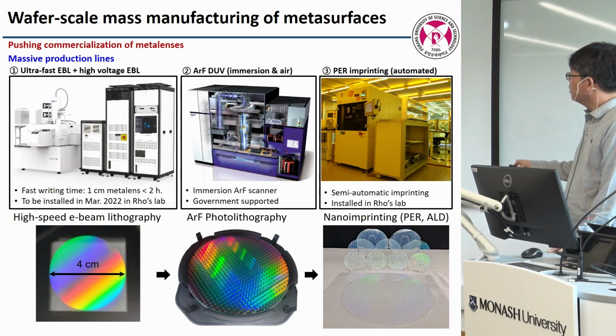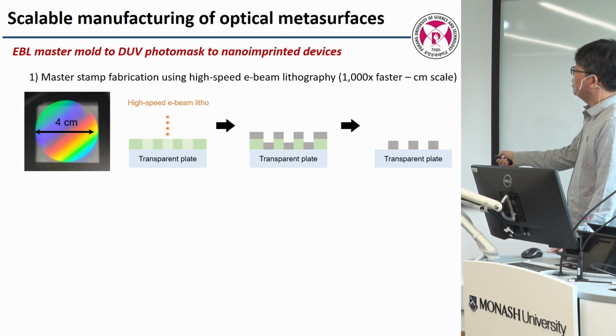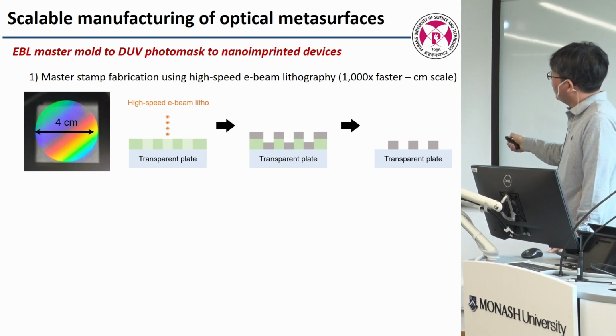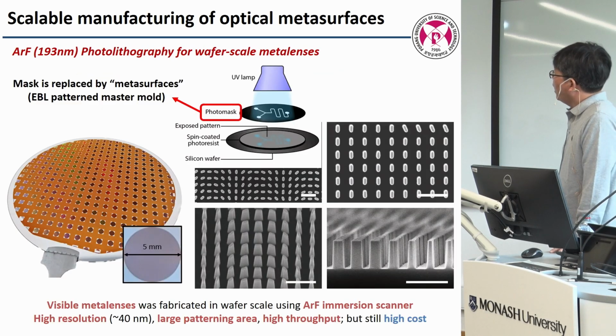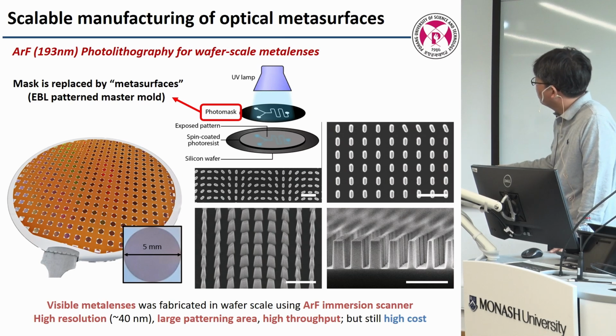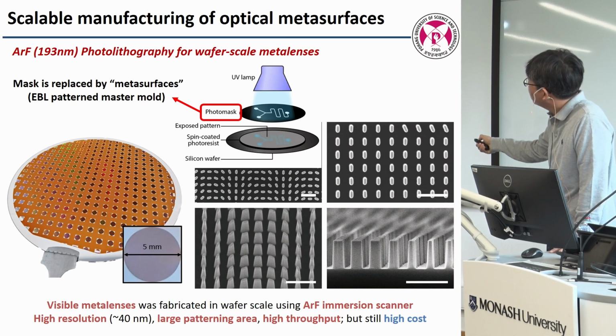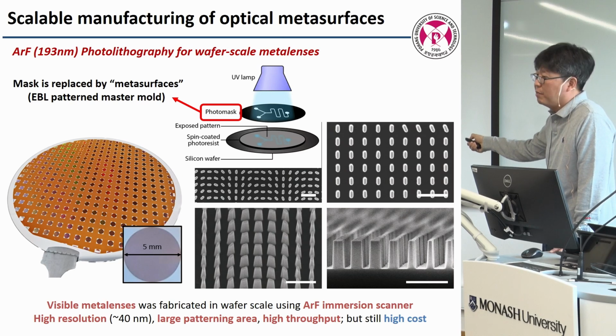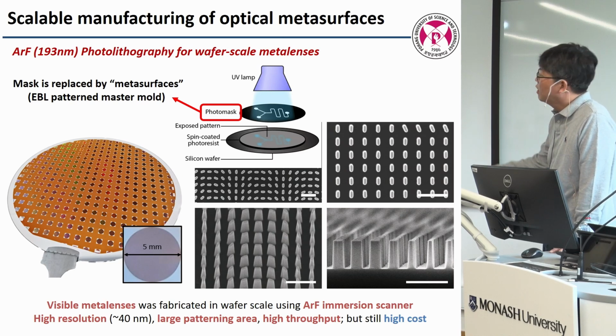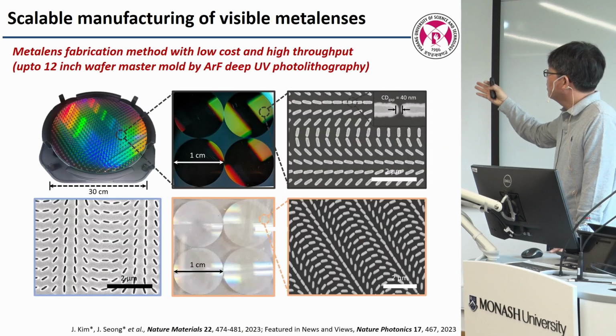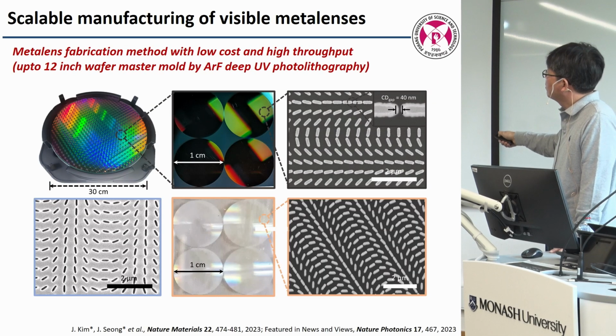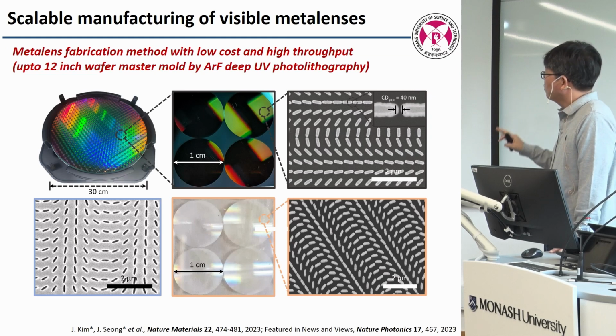But we can go further using this as a master mold. We can do another nano imprinting into a flexible, transparent substrate. So this is the e-beam step, typical, but getting faster as technology develops. And this is a photo mask for photolithography. And this will be the metasurface now, a 4 centimeter one. And then the projection happens like that, so an array of 600 metal lenses onto the 12-inch wafer. So you can stop here.